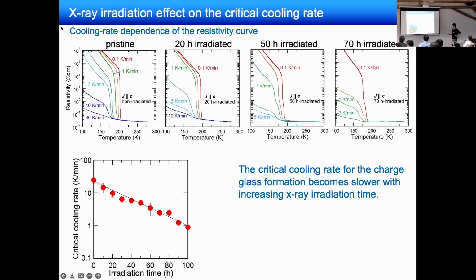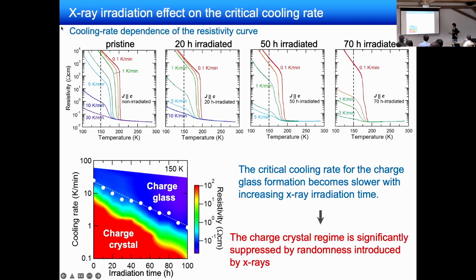Okay, and in order to quantitatively evaluate the charge crystallization progress for the X-ray irradiation, we plot the amplitude of resistivity at 150 Kelvin within the critical cooling rate versus irradiation time diagram. This red color indicates the large resistivity regime corresponding to the charge crystal states, and this blue color corresponds to the charge glass states. It can be clearly seen that the critical cooling rates plotted by white colors separate the two states. From these results, we can say that the charge crystal regime is significantly suppressed by randomness introduced by X-ray.